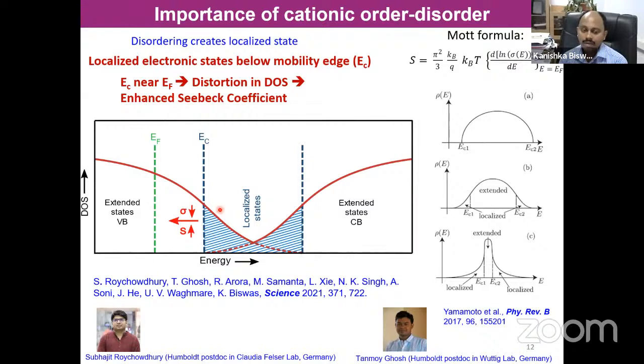But you see, if the mobility edge moves towards the Fermi level, we'll have a distortion in the density of states. Okay, so that goes away from a normal parabolic dependence, and will have features like this. From this Mott equation, you can see the Seebeck coefficient is directly proportional to the first derivative of the density of states at the Fermi level. The first derivative of the density of states is nothing but the slope, right? So if we can create a high slope at the Fermi level, we can have a jump in the Seebeck coefficient. That is basically called the resonance level.